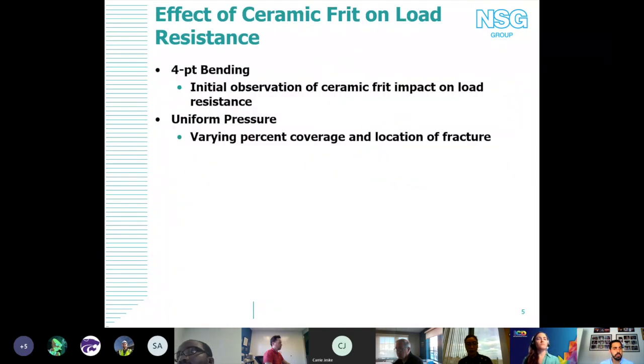So what I've done is I've just taken 2 phases of what my research was to give an idea of what this load resistance reduction looks like. Initially we did some small sample 4-point bend tests, and we use this just as an observation of, does ceramic frit impact load resistance? Does it matter which surface it's on? How much? Kind of just as a gauge of, is there an actual change in mechanical failure whenever you apply ceramic frit? And then the second are uniform pressure tests, more what you would see in terms of a 4-side simply supported piece of glass. And in this, we checked varying percentage coverage, and we're able to see where the location of failure was with regard to the frit coverage on the glass. So we'll go over both of those.